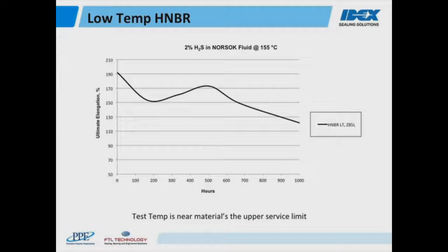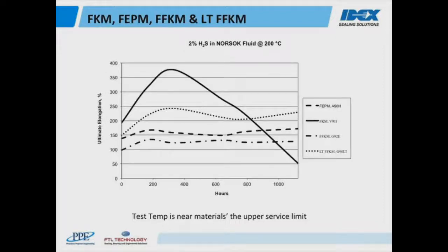This graph shows the higher temperature fluorocarbon elastomers. Here we have a test at 200 degrees Celsius versus the 155 degrees C as we saw in the previous slide. The higher temperature allows us to observe property changes faster and provide a level of confidence that the material will be suitable in a similar service environment.